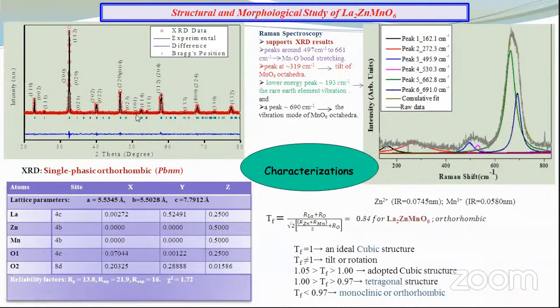So this is the crystal structure. These are the X-ray diffractograms, and this is the Rietveld refinement. This straight line below the experimental and measured data indicates the good quality of fitting of the Rietveld refinement, and results are given in these tables. In the present case, the material crystallizes in the orthorhombic Pbnm structure. And this Raman spectra also supports our XRD refinement. There are various peaks in the Raman spectra here, which indicate the rotation or tilting of MnO6 octahedra.